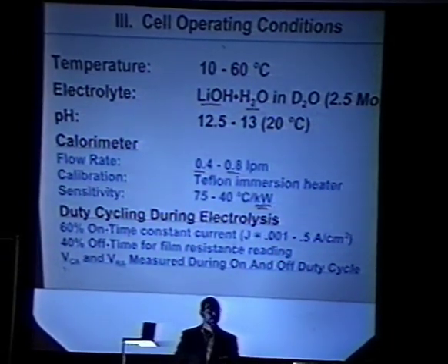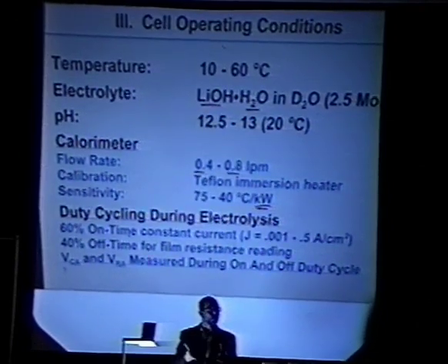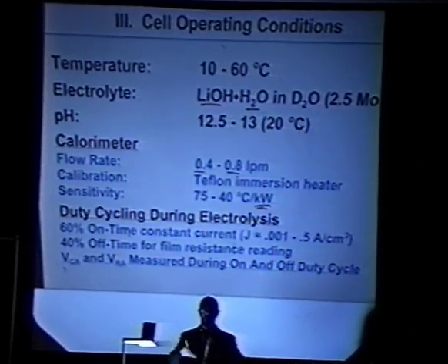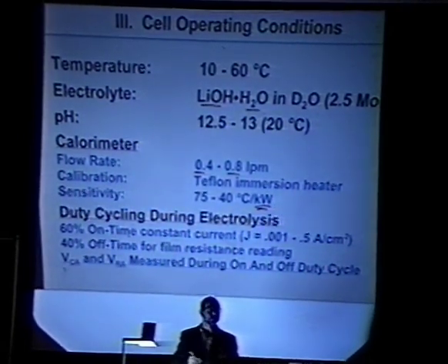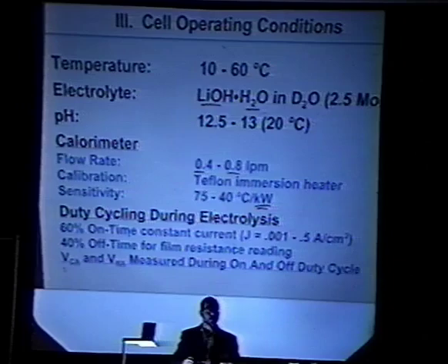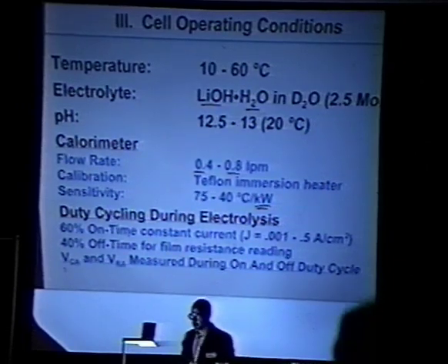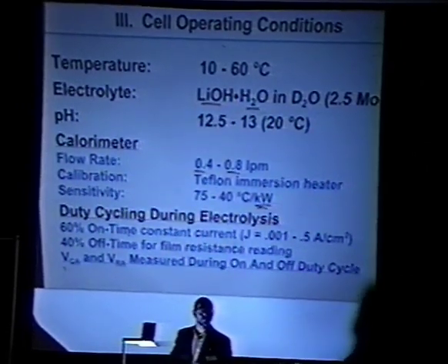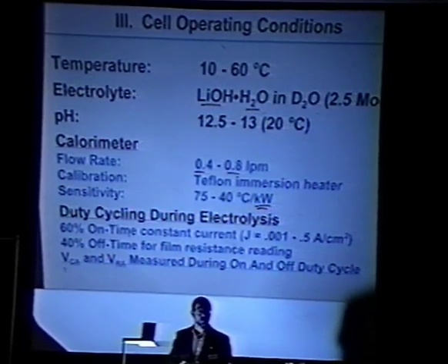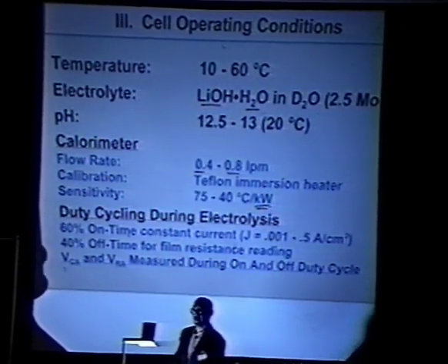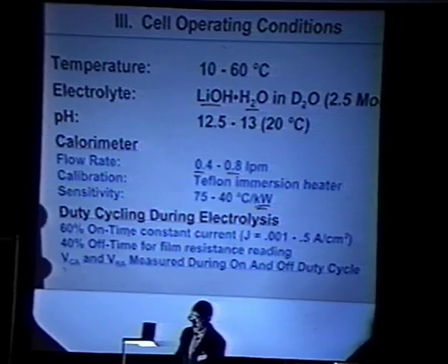My motivation for making the calorimeter this heavy duty was to make sure I didn't get in any runaway type of situation where this thing just boils away and you lose all your data. So I kind of opted to make it not a very sensitive calorimeter. It's designed to remove a lot of heat. And so it's not real good for picking out, in fact, less than about 20 watts. If you get more than 20 watts, you'll definitely see it. 5 watts is something buried in the noise with this thing.